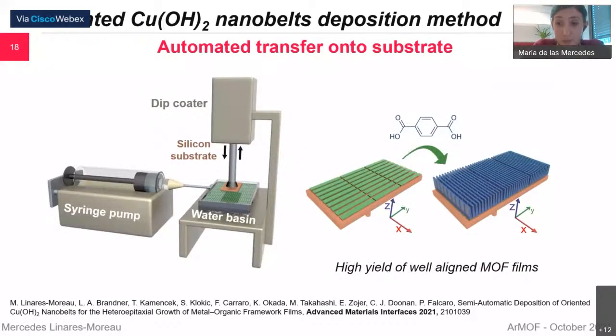So what we did was to improve the deposition procedure and introduce a dip coater to control the final step and to be able to control the immersion depth and immersion speed. And also we explored different injection volumes with the syringe pump and tried to obtain the best coatings that we could get.